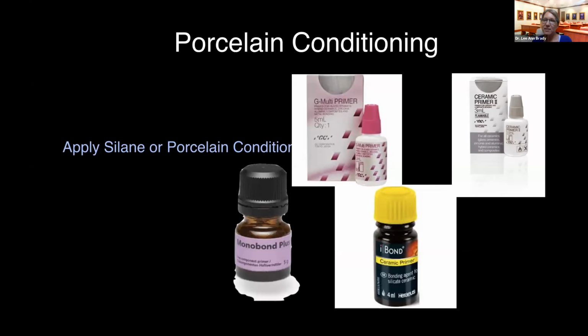Is there a decreased efficiency of bonding with Monobond Etch and Prime? No. The scientific studies show that you get the same bond strengths to the glass as if you're using hydrofluoric acid cleaning and then using Monobond Plus. So it works really well.